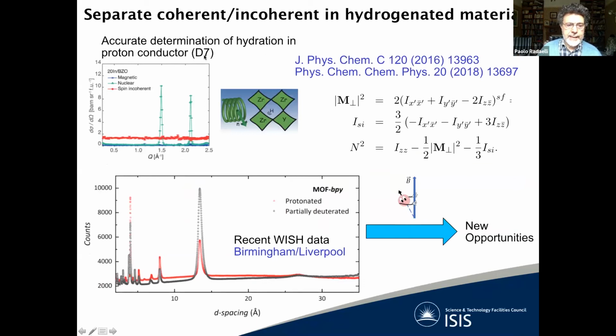And then you can separate extremely well the three components. So the magnetic component, and here I'm looking at the panel on the top left, in this case there wasn't any; the nuclear coherent component here in gray, and the spin incoherent, that is the hydrogenous background, in red. And using this technique, you can precisely titrate the amount of hydrogen in the sample, because you know that this signal comes entirely from hydrogen in hydrogen-containing samples.